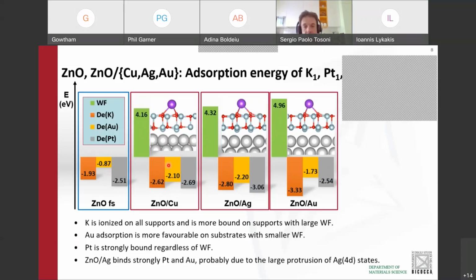is smaller. Platinum, once again, does not display a clear dependence with respect to the work function. It is worth noting that the trend with respect to the work function doesn't really hold true for the case of ZnO on silver. Here, both platinum and gold are bound in a way more strongly than one could expect based on a work function argument.